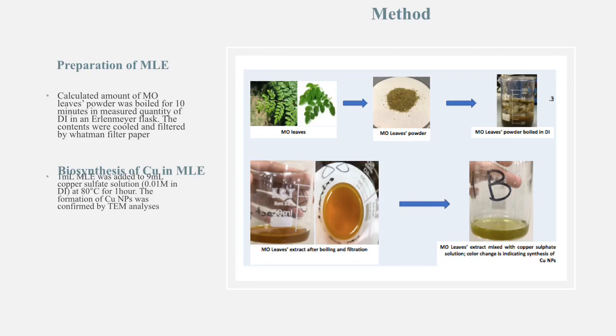Powder was boiled for 10 minutes in a measured quantity of deionized water in a Erlenmeyer flask. The extract was cooled and filtered by Whatman filter paper. For the biosynthesis of copper nanoparticles using Moringa oleifera, 1 milliliter of Moringa extract was added to 9 milliliters of copper sulfate solution at 80 degrees Celsius for 1 hour. The formation of copper nanoparticles was then analyzed by TEM.